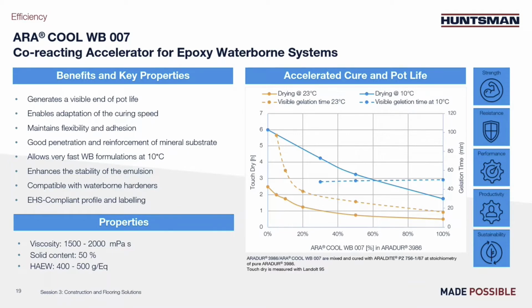Still on the waterborne subject, generally waterborne systems are not so fast to cure, and often there is a demand to speed it up. But unlike traditional systems, standard accelerators do not work very well, as those have to be added as a third part. So this new ARA COOL WB 007 is water soluble, so it's mixable with any waterborne hardener. It maintains on top of the acceleration a good flexibility, and it has a good EHS profile.